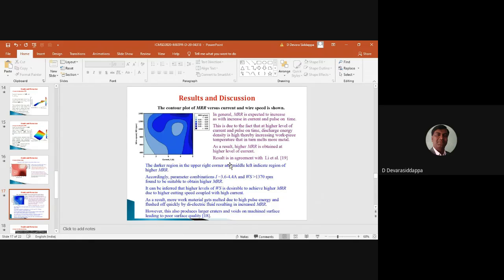So, in general, it is expected that MRR increases with the increase in current. This is also due to the fact that at a higher level of pulse on time and current, the discharge energy density is more, resulting in increased temperature of the workpiece, which in turn melts more material. That's the main reason for having higher MRR at higher levels of current. The result presented here is also in agreement with some researchers, Lee and others.